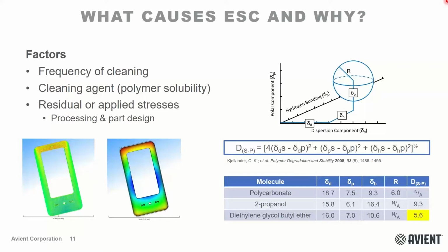And so what you can do is take a solvent or a reagent and compare its intermolecular forces with that of the polymer solubility sphere. It can give you some indication as to whether or not that reagent is going to be a good solvent, a theta solvent, or a bad solvent. There's an equation that's fairly simple to use, and a lot of these Hansen solubility parameters are available online. What this equation does is tell you the distance of the solvent in relation to the center of the solubility sphere. When the distance between the solvent and the polymer is smaller than the radius, or inside of the radius, you might be able to conclude that that would be a good solvent, or at least a theta solvent, for that polymer.